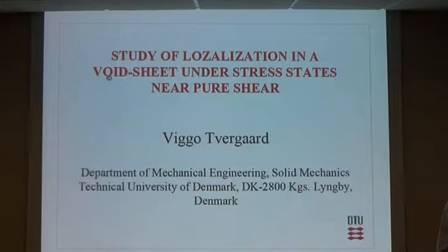Now, to look at another situation with small stress triaxiality, called pure shear. This is a situation where you have tension in this direction and compression in this direction. If the compressive true stresses are equal to those in tension, then it is pure shear. That means there's 0 stress triaxiality. This is really a unit cell representing a periodic pattern of voids.